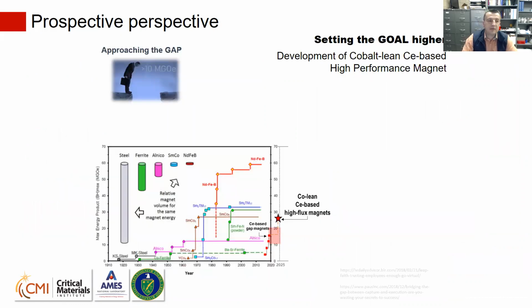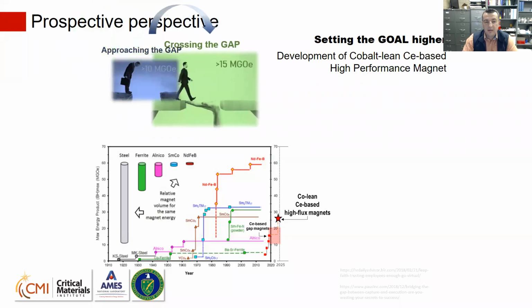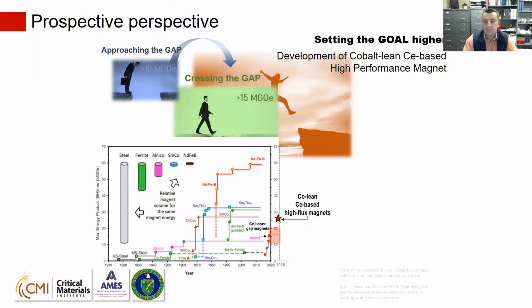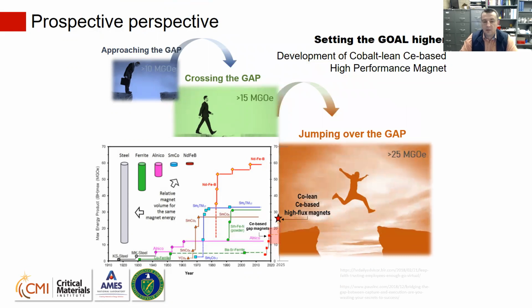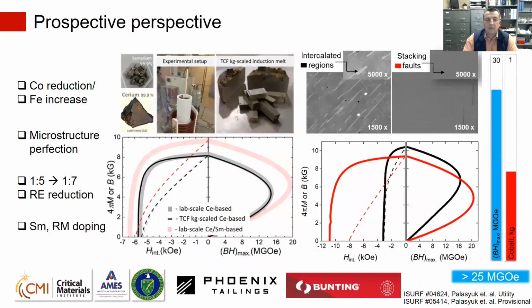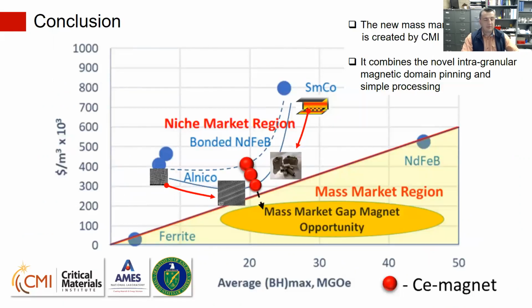So then let's talk about future perspectives, if you want. We were very scared to approach the gap. Actually, we quite successfully passed already the gap, and we are thinking about now crossing the gap and performing over 25 megagauss-oersted. And these are our preliminary results, in fact, which are showing that this is possible. And if we were able to produce on kilogram scale, with a similar method, our material, then the indicator of cobalt per megagauss-oersted is becoming more and more positive. And in fact, we are starting to address the gap magnet problem.